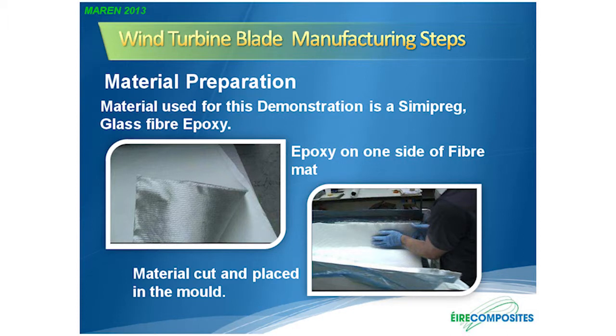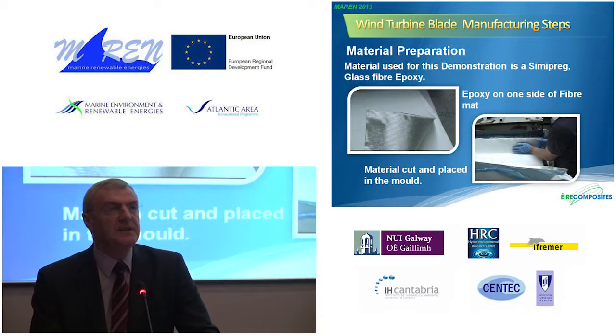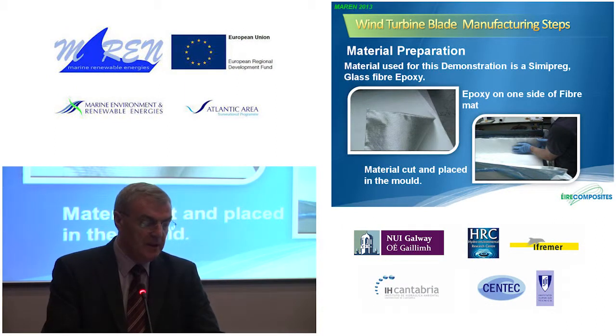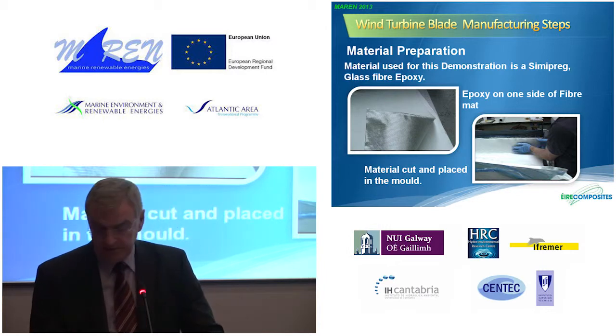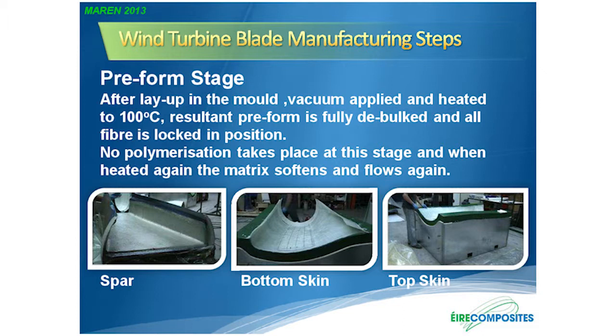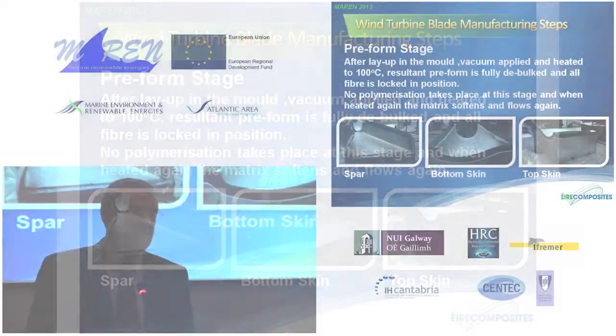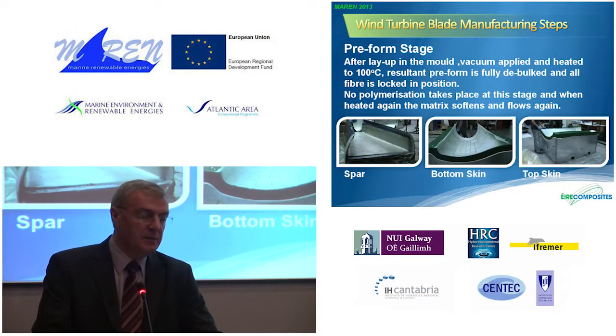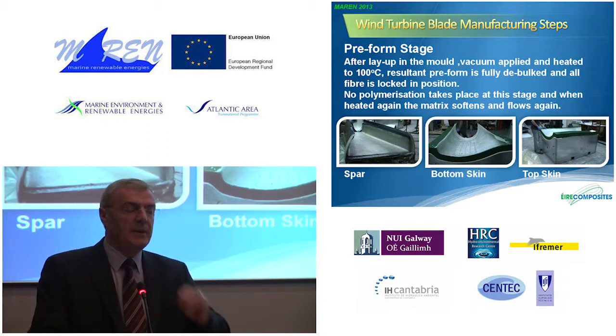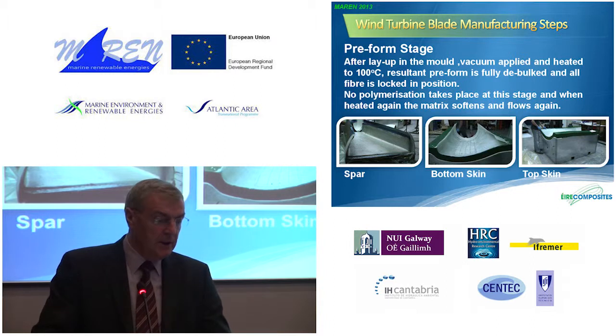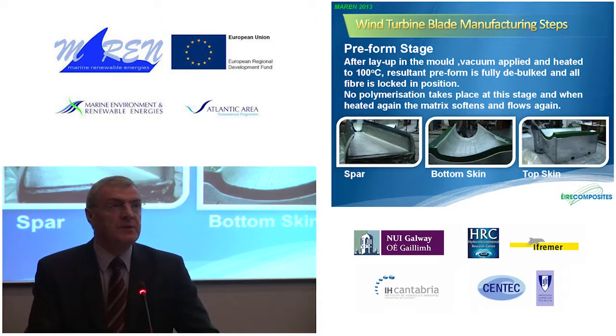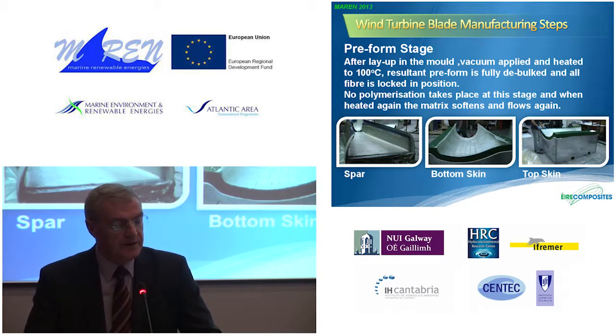So how do you do all this great stuff? First of all, the first step is to prepare the material. The epoxy powder in this case is deposited on one side of the fibre mat. That is then cut to size and placed in the mould. The next step is your preform stage: once you have it laid into the mould, you cover it with a vacuum bag, apply a vacuum, and heat it to 100 degrees. At that temperature, you can fully debulk the laminate, you remove all the air, and also you lock the fibres in position, and they won't move from where they are after that.